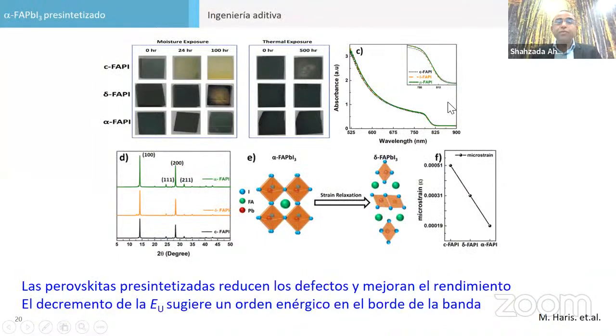So having done delta FAPI3, we are now working on an alpha FAPI3 powder, and we found this is relatively more stable, because when we make the powder, we heat it and it converts to the alpha phase. The conventional FAPbI3 that most people were using is dark and absorbs light, but after 24 hours and 100 hours, it became yellow or transparent. So it will not absorb light and will not be good for solar cells. Delta FAPI is also good for 24 hours, then it slowly degrades. So now we are working on alpha FAPI. You can see it remains black for 100 hours even in an open atmosphere. Black means it absorbs light, so it can work for solar cells.